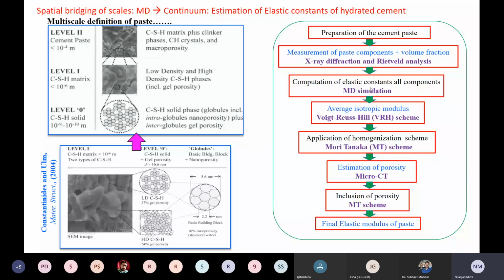Now, if you look into the scanning electron microscope of the structure, you get a lot of different things. As I mentioned before, you get tobermorite, ettringite, gypsum, and a lot of different things in there. Okay. So what we did in that case, in order to bridge the scale, is that we took all of these materials within your cement paste. Obviously, we performed an XRD and then found out what are the related percentages of those materials.